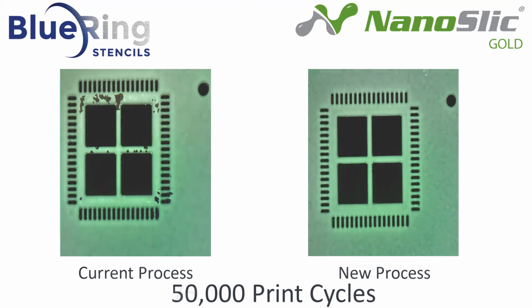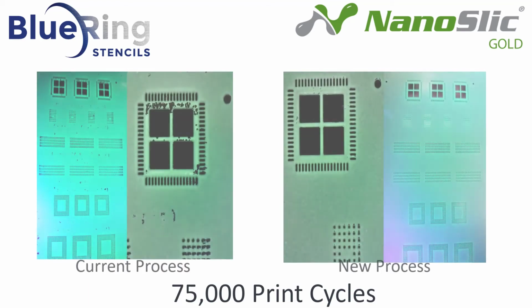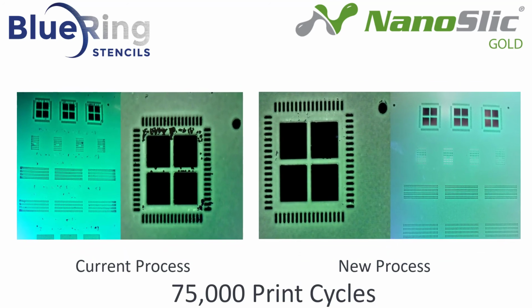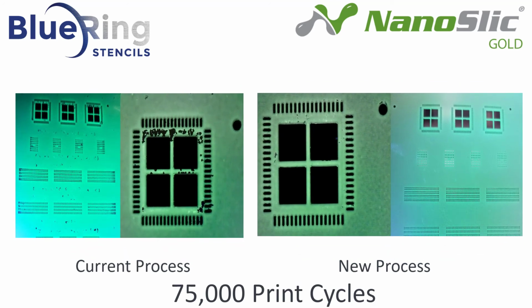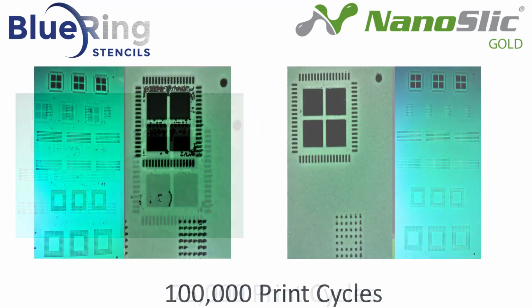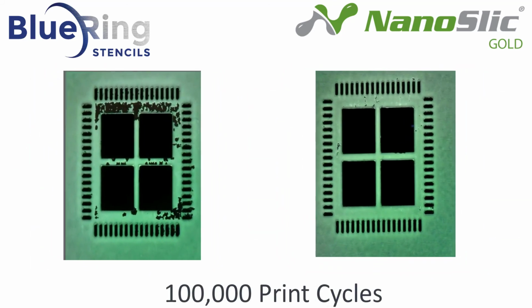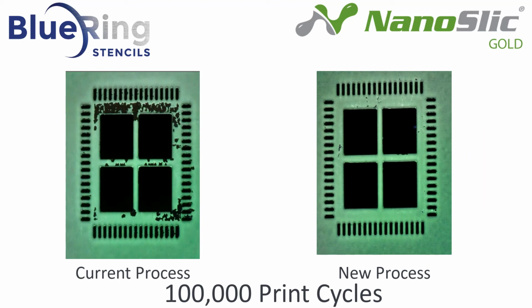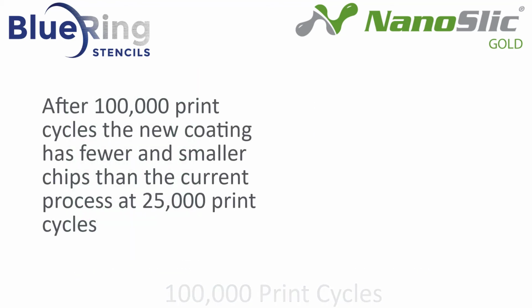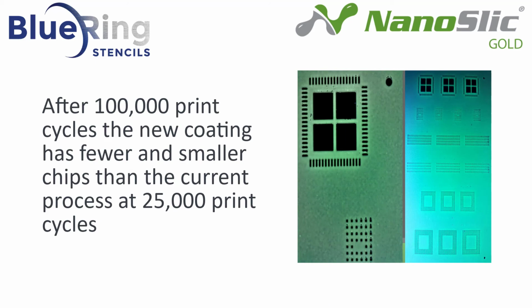At 75,000 print cycles, you can see the current process continues to degrade, and we start to see some small chips around the QFN and micro BGA on the modified surface coating. The differences are dramatic. The last slide we'll look at here is after 100,000 prints. The current process coating has worn out, and even after 100,000 print cycles, the new modified surface coating is holding up very well. After 100,000 print cycles, the new modified surface coating has fewer and smaller chips than the current